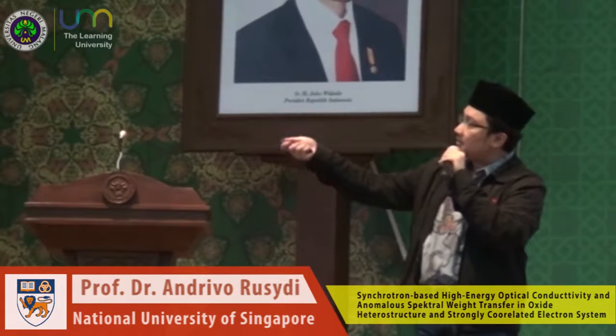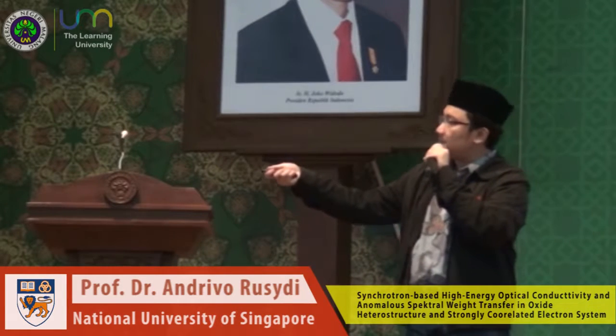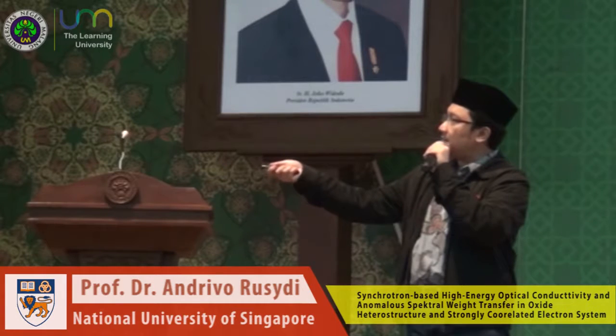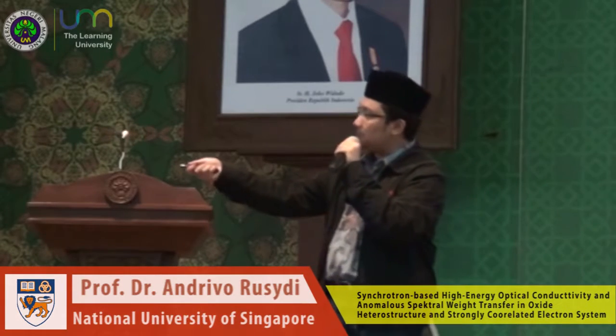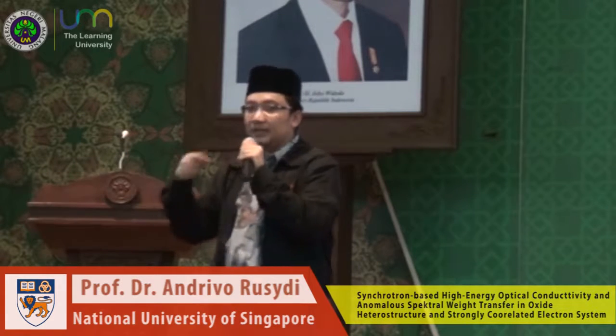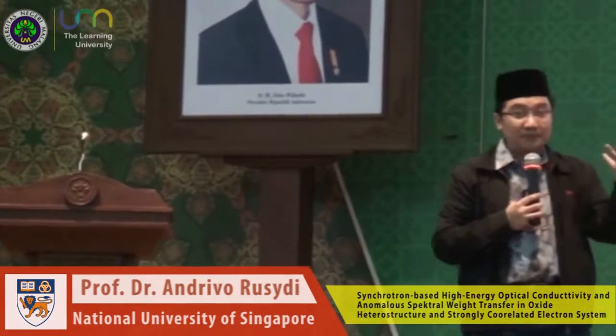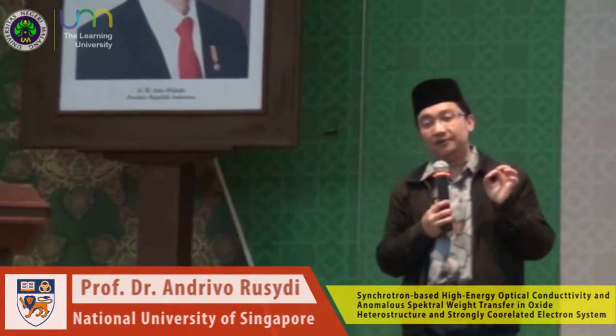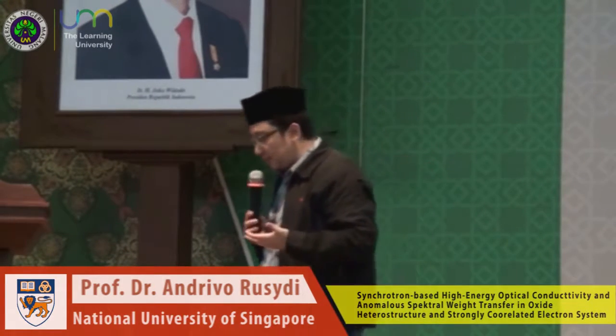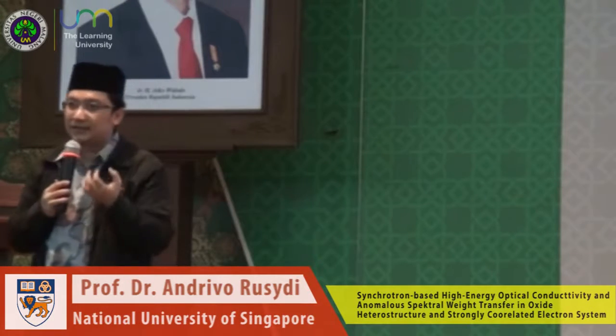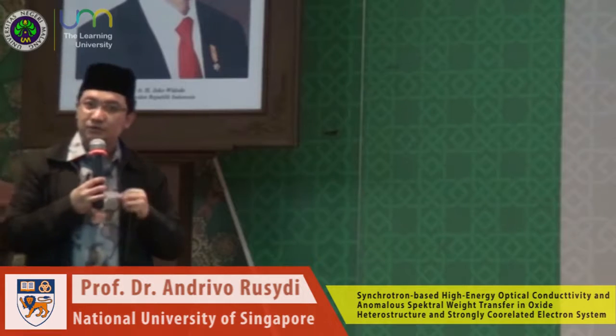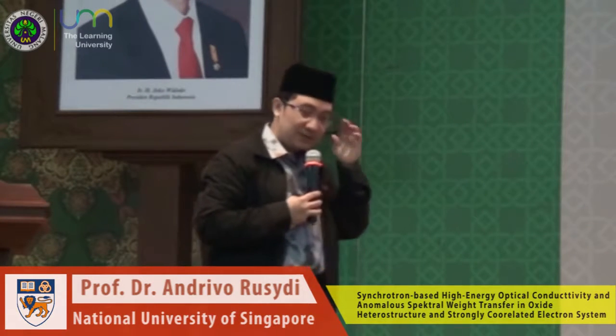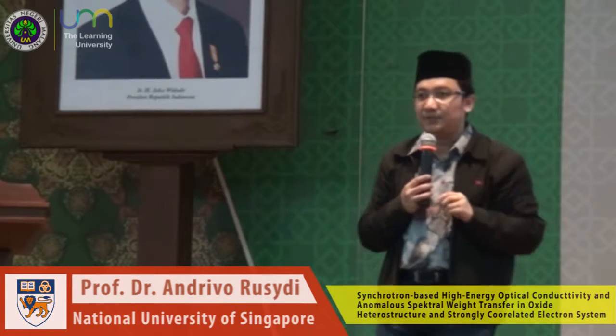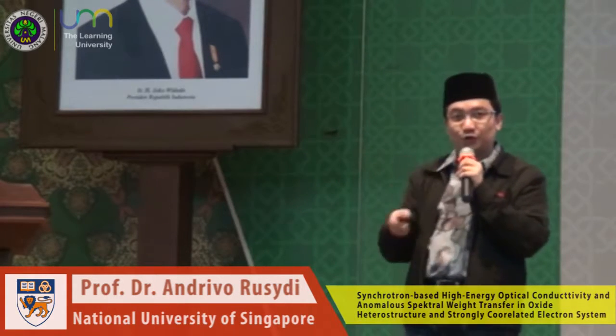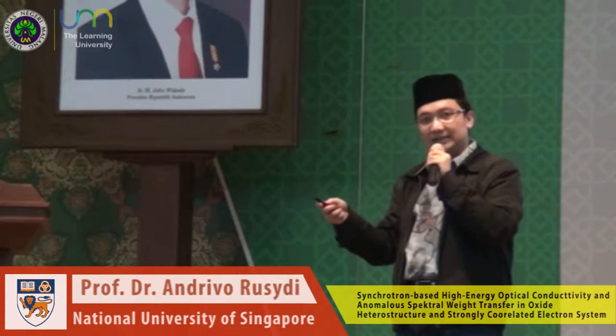But all these papers agree, or at least one of the papers states, that the existence of an excitonic effect had been explicitly mentioned to be absent. That was a Physical Review Letter in 1970, and this was referred to by many papers until before our publication. Exciton was absent. And exciton itself involves electron-hole interactions, and some excitons, what we call resonant excitons, even involve electron-electron and electron-hole interactions. If that happens, you cannot call STO a passive material anymore. We want to find out if there are electron-hole interactions strong enough to create an exciton in STO.